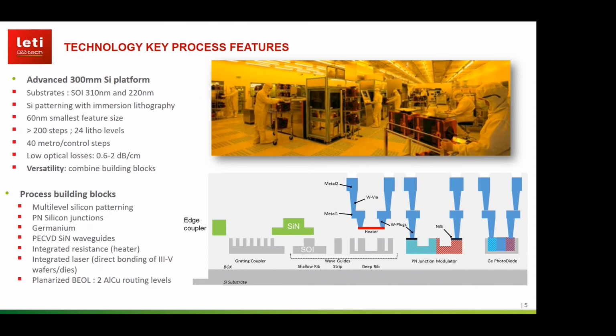So first, the silicon photonics platform. We have developed a silicon platform for 300 millimeter wafers. You see the cross section here with first the SOI level. We can start with 310 nanometer thick or 220 nanometer thick SOI. We use immersion lithography to pattern the silicon with a feature size down to 60 nanometers. To realize this cross section, it's a very long process. We have more than 200 steps and 24 levels of lithography, and there are several process building blocks to achieve this cross section. Several levels of patterning for silicon, dopings for PN junctions, germanium for photodiode, silicon nitride if it's needed, and then a two-level back end of line.